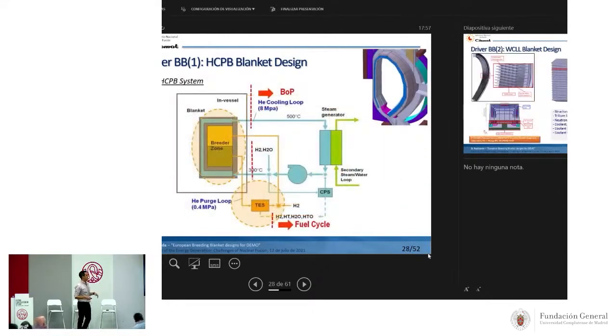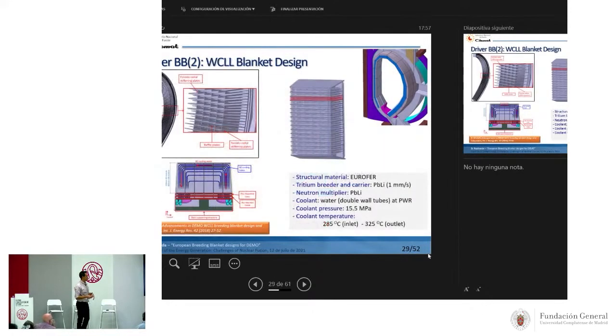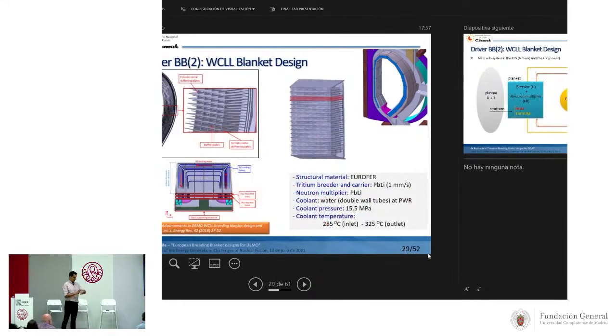Okay, and this is another scheme of the same, more complex. And this is the second driver blanket. This is the WCLL. In this case, we have as breeder the liquid metal, the lead-lithium, and as coolant we have water, at these conditions. I will explain right now. In this case, we also use Eurofer as a structural material. In this case, the neutron multiplier is the lead-lithium itself.